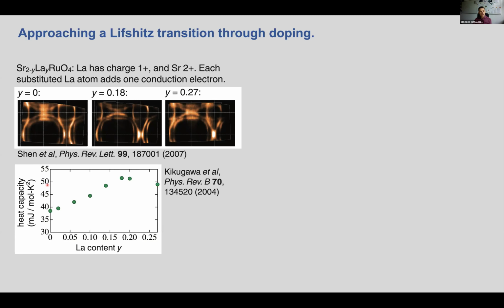The heat capacity, the Sommerfeld coefficient, increases as lanthanum is substituted into the system and reaches a peak at about 0.2. So in other words, at a lanthanum content of about 0.2, the electronic heat capacity is at its maximum. This is about where this transition occurs.